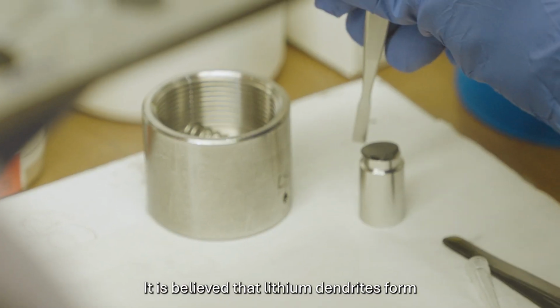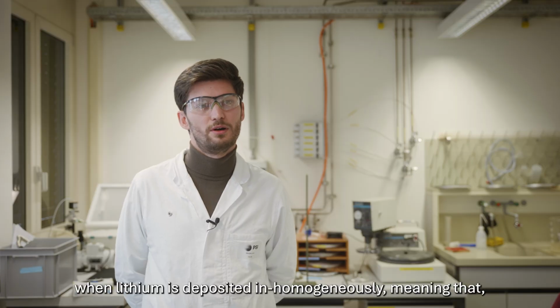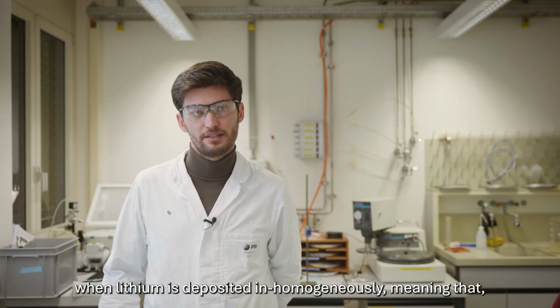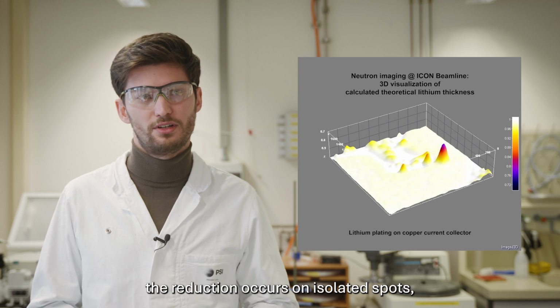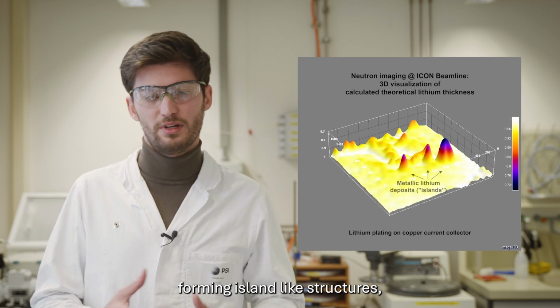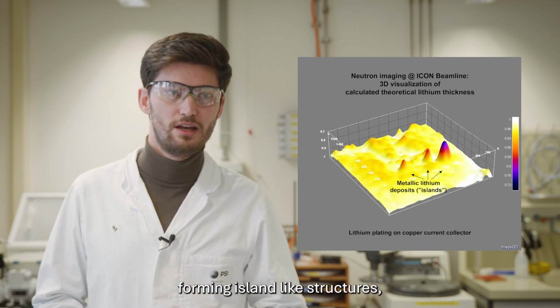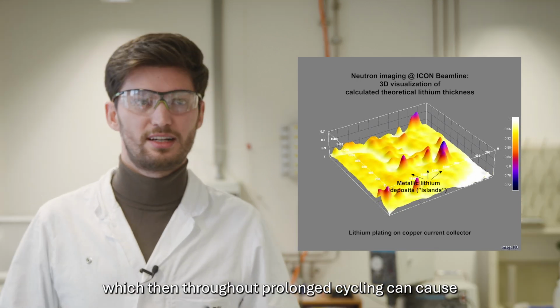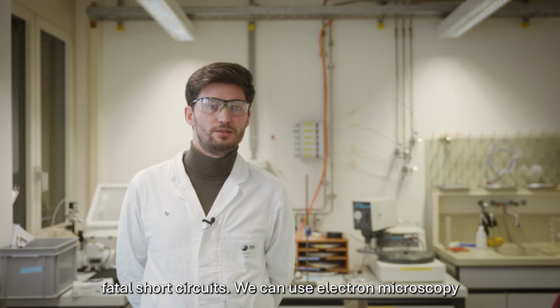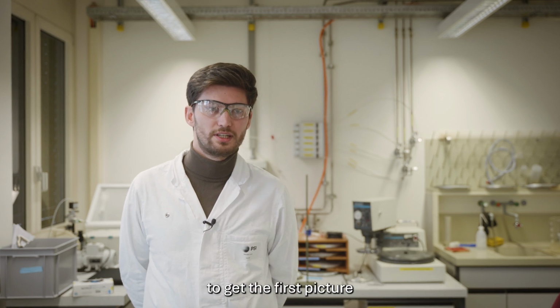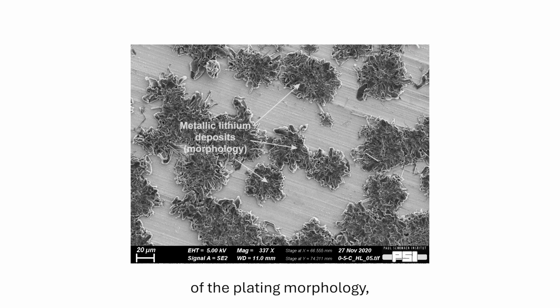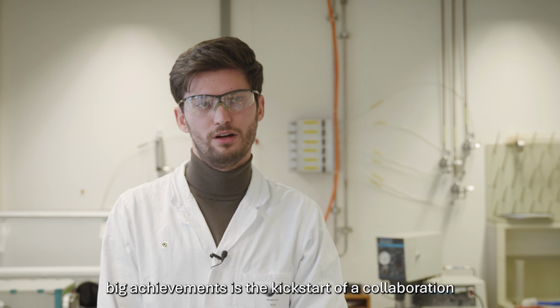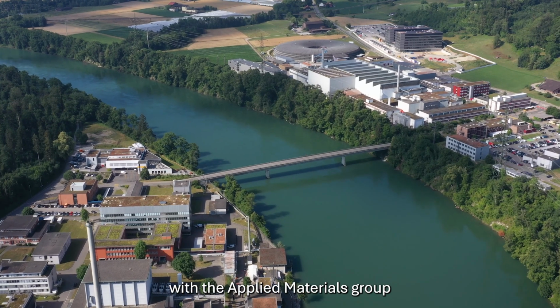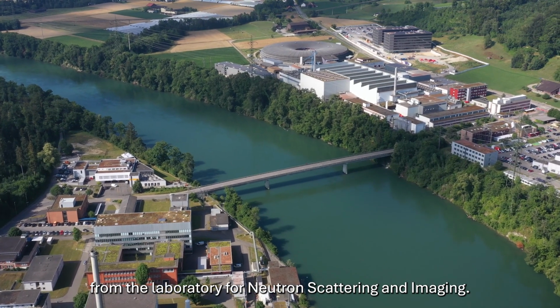It is believed that lithium dendrites form when lithium is deposited inhomogeneously, meaning that the reduction occurs on isolated spots, forming island-like structures, which then throughout prolonged cycling can cause fatal short circuit. We can use electron microscopy to get a first picture of the plating morphology, the deposition morphology, once we open the cell. One of our big achievements is the kickstart of a collaboration with the Applied Materials group from the Laboratory for Neutron Scattering and Imaging.